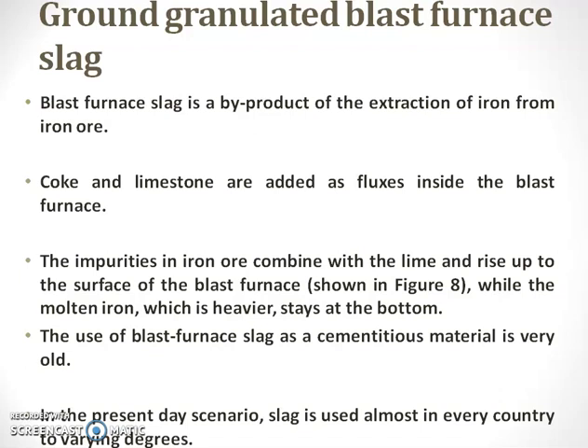In India, it produced about 7.8 million tons of blast furnace slag. All the blast furnace slags are granulated by quenching the molten slag by high power water jet, making 100% glassy slag granules of about 0.4 mm in size.